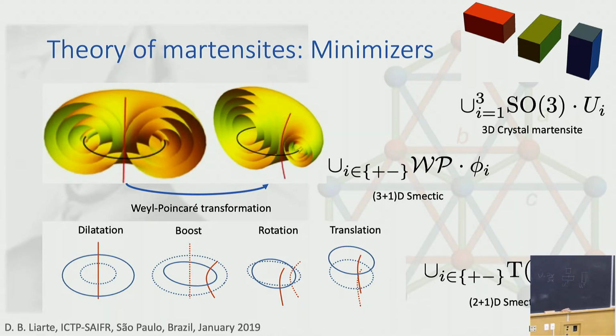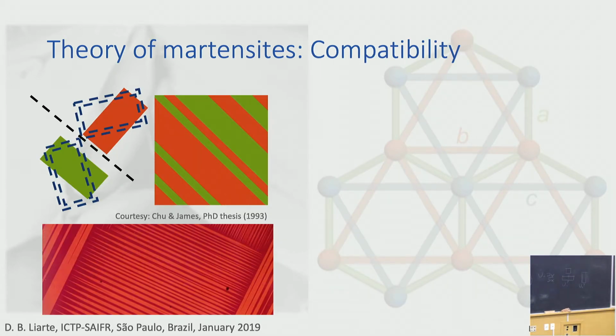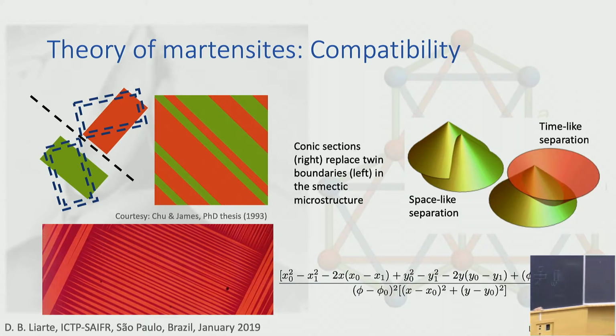So the last ingredient of the theory of Martensites is the compatibility condition. I've shown you before how the variants of the Martensites will rotate and form twin boundaries and form these fine laminates in order to minimize the free energy while you have some constraining boundary conditions. Now, for the Smectic case, for instance the 2+1 dimensional case, in order to find the compatibility condition between two different variants of the Smectic, you have to find the intersection between cones.